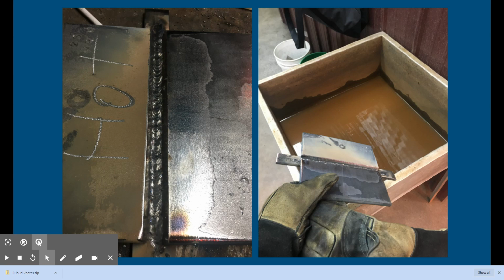So if this is a bend test you're putting a lot of time and energy into, and you want to pass it, let it cool naturally. Let it sit. For your vertical welds, I didn't point it out on the WPS, but there is an interpass heat temperature, so you want to let that cool down on your vertical welds in between your passes. It's to the student's advantage to do that. On your horizontals, I like to run them as hot as I can, and I'll just rip those across. But the vertical ones, you definitely want to let those cool down.